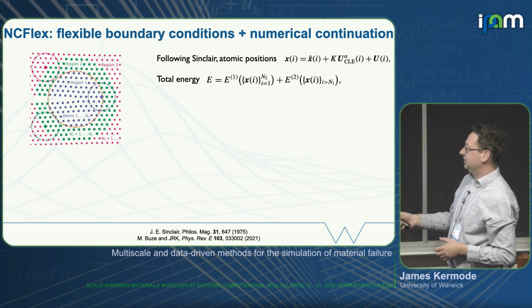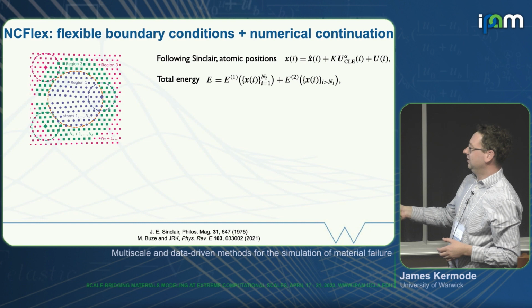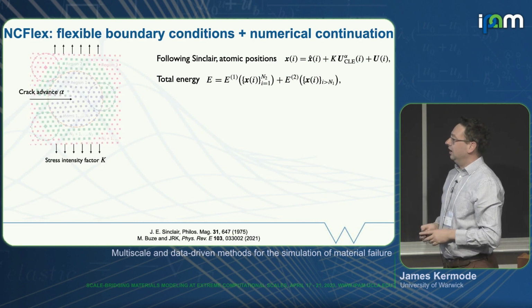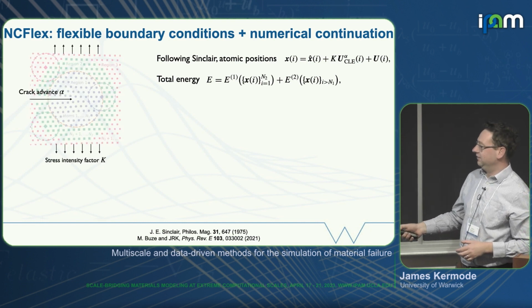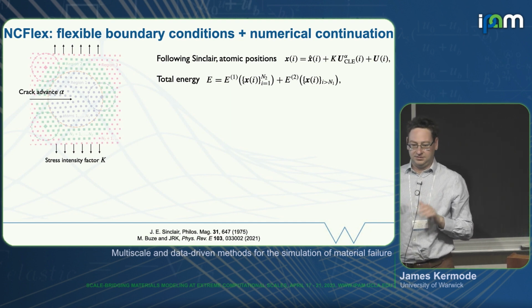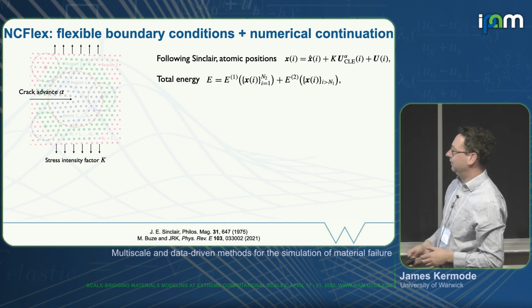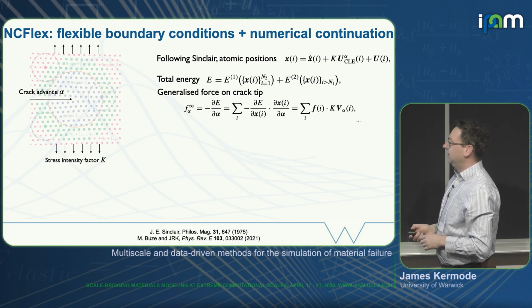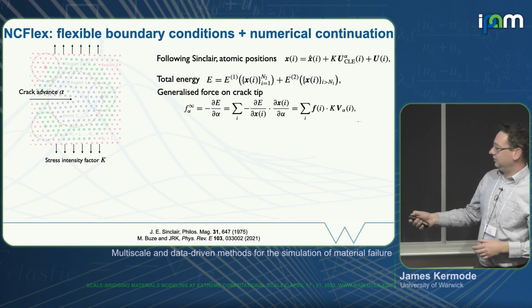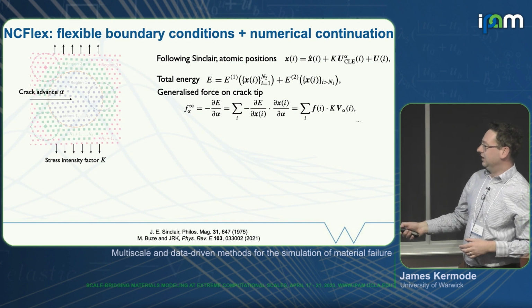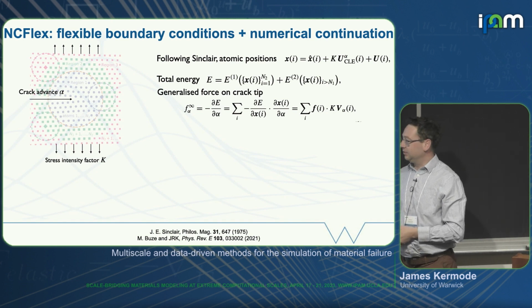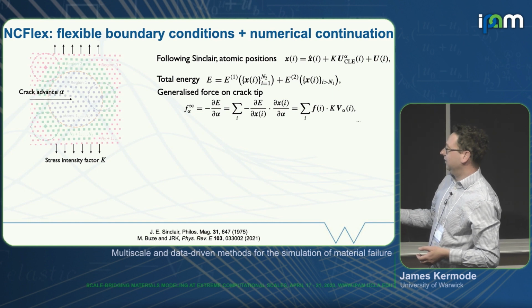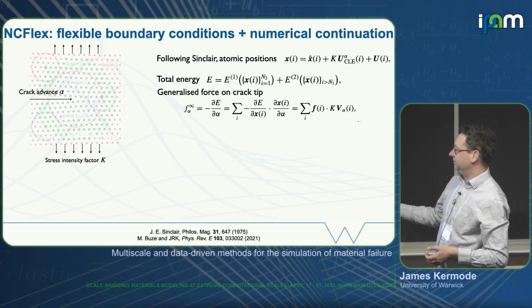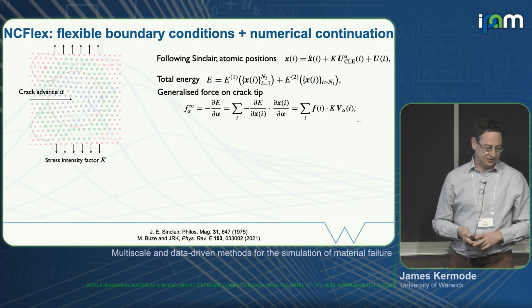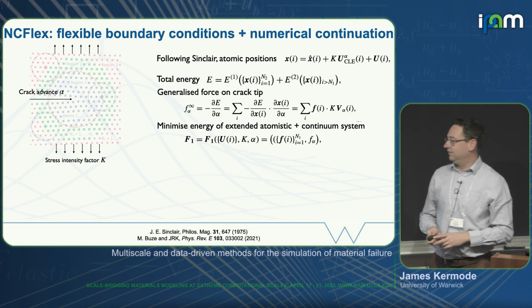We can write down a total energy for the system with contributions from the atomistic part and from the continuum part. That's parameterized in terms of the position of the crack, which is just a scalar alpha, and the applied far field stress intensity factor. And then if we take a derivative of this total energy with respect to this crack position, we can get an effective generalized force on the crack tip. And it turns out that this just involves summing up atomic forces multiplied by derivatives of the continuum linear elastic displacement field, which we have analytically, and so we can use that to drive the extended system.